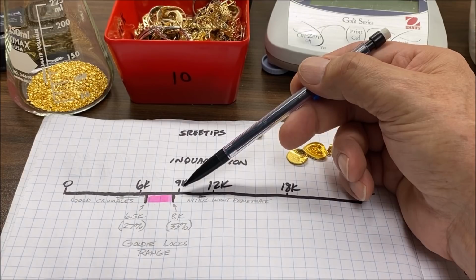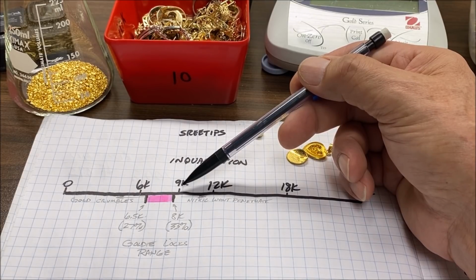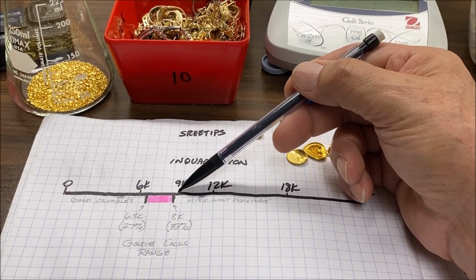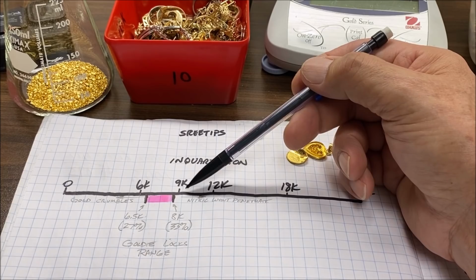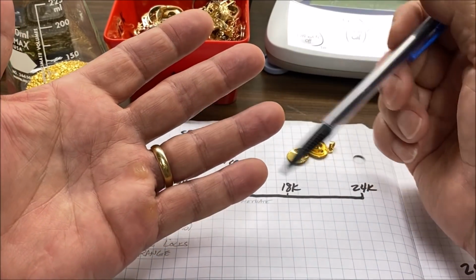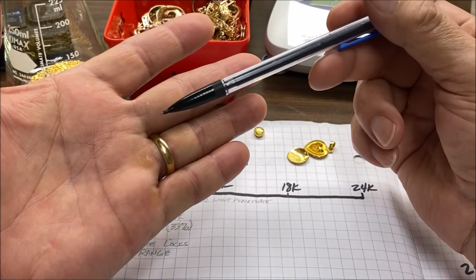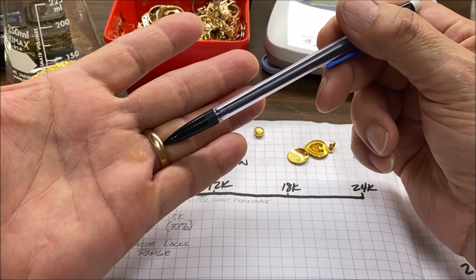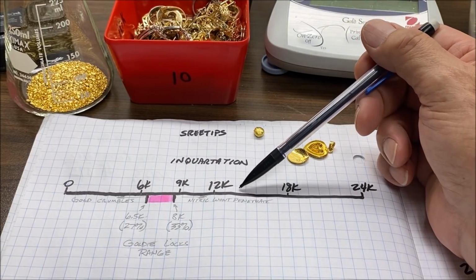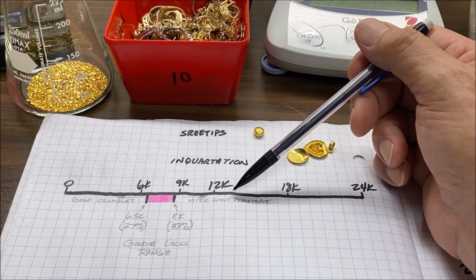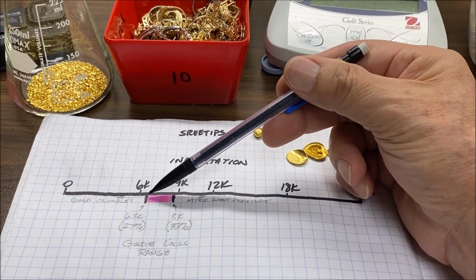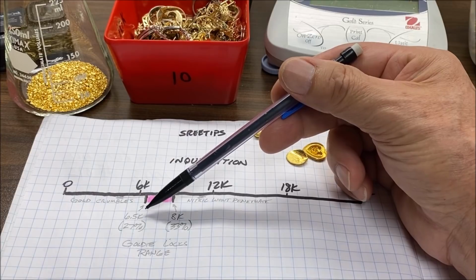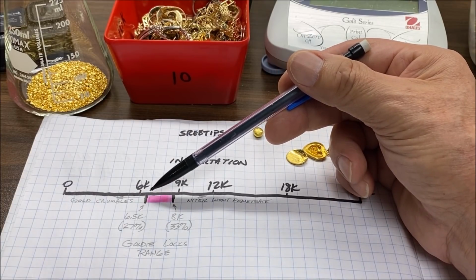On the other end, if we go above this level right here, then the nitric acid takes longer to penetrate into the gold, and increases the time required that the inquarted gold must stay under the boiling nitric acid. And anything above 9K, and you've seen me do it, I put my wedding band in boiling nitric acid, and with the carat of gold this high, 14K, it'll just sit there and it will not be affected by the boiling nitric acid.